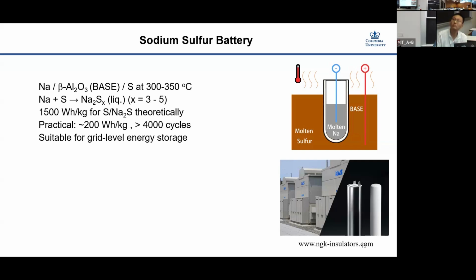In this case, the two electrodes, sodium and sulfur, are molten liquids, and they are separated by beta alumina, which is a combination of sodium oxide and aluminum oxide. The overall reaction is sodium plus sulfur forming sodium polysulfides. If we can completely use the full reaction range, which means we form sodium sulfide, then in theory we can get 1500 Wh/kg. Practically, you can only go to x equals 3 to 5,